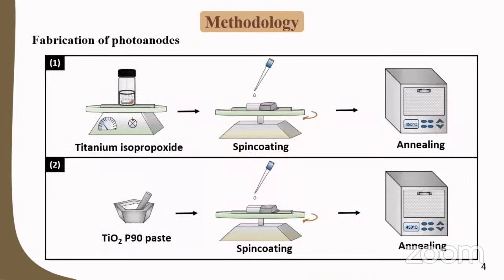Methodology. This is the procedure followed in preparation of the photoanodes. First, a pinhole-free compact layer of TiO2 was deposited on a pre-cleaned FTO glass substrate by spin coating a mixture of titanium isopropoxide, propanol, glacial acetic acid and nitric acid in an ethanol medium at 3000 rpm for 1 minute. The substrate was sintered at 450 degrees Celsius for 45 minutes.